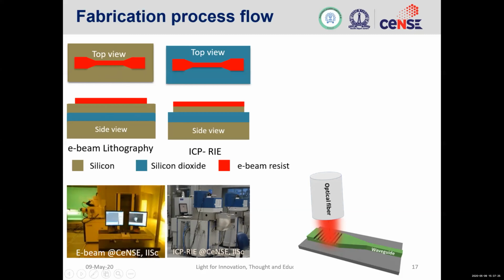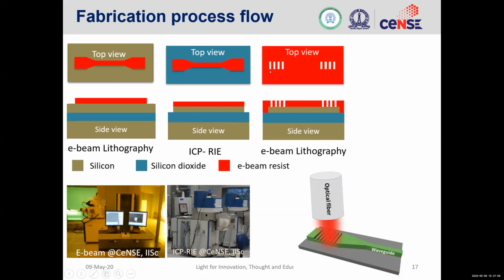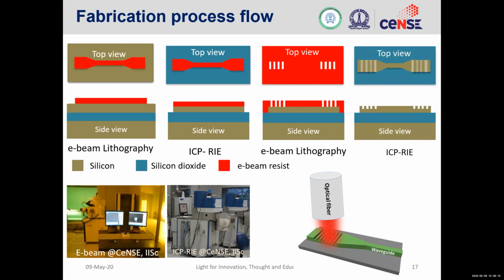The next step is to do etching. In the etching, you put it inside an RIE, and the complete silicon gets removed in this portion. You time it in such a way that when it reaches silicon dioxide, you turn off the process. So the waveguide, this part, is achieved. The next step is to pattern these corrugating structures. In order to do that, we do another e-beam lithography where we pattern only in this portion. After patterning this and putting it in the developer solution, this part gets removed or dissolved. Then you do another RIE, and then you remove the photoresist. This is the complete process flow for making a waveguide and the coupling structures.